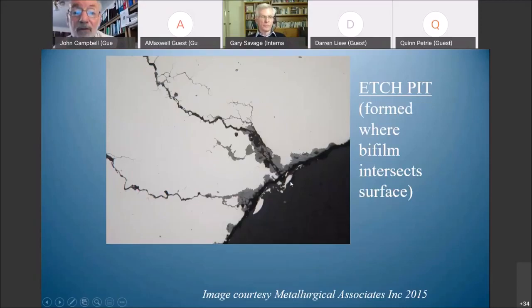The cracks were here first, and the etch pit forms because of the presence of the cracks. So again, the cracks are pre-existing. They're put in by us foundry people, by the way we cast our metals. So the etch pit is merely telling you that there's a bifilm emerging at this place. So the etch pit is a tiny defect, but the crack can be enormous at the back. And it's that has to be feared, not the etch pit itself.